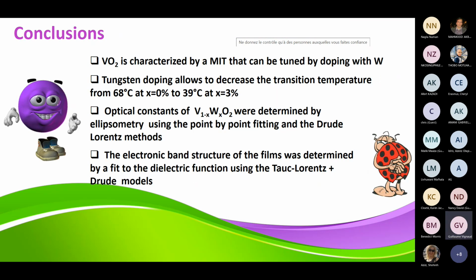Okay, and so, conclusion now. I hope that we have convinced you that with doping with tungsten, we can decrease the transition temperature, and above all, that if you use combined techniques like X-ray diffraction, reflectivity measurements, and ellipsometric measurements, you can get very good quantitative information about what's going on in your film. But there is a price to pay every time. Don't think that you will get it just like this. You will have to do some calculations and go through the theory. Otherwise, you cannot understand what's going on.